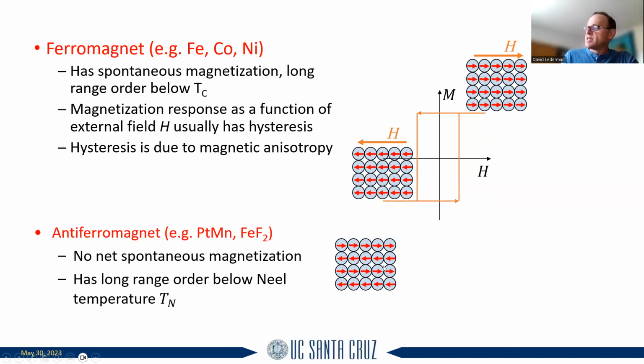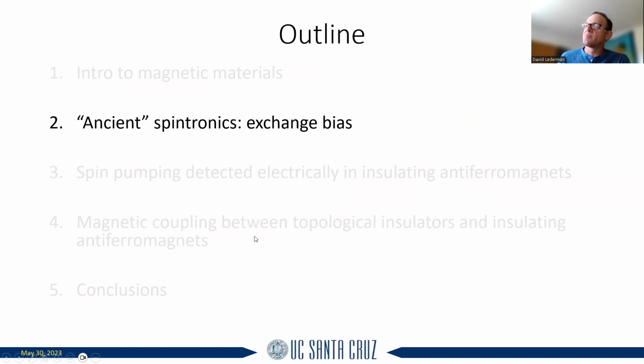And even though it doesn't have a very large, or actually ideally 0 magnetization, you can still tell that there's some long range magnetic order in this material. Okay, so you can't really plot something like a hysteresis loop as you do in a ferromagnet, which has a spontaneous magnetization, because the spontaneous magnetization here is 0, but there is order. Okay, so that's what I wanted to say, just a very brief outline of this.